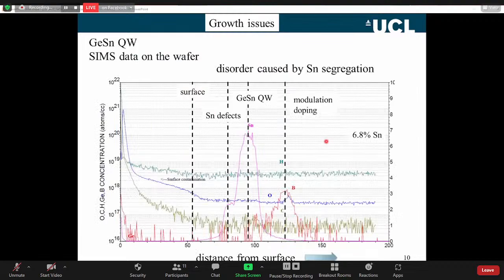When we look at what we've grown, we use a technique called SIMS. I think it's secondary ion mass spectroscopy, so it's a good way of measuring what's in your device. But there's a lot of information here. On the y-axis, I'm plotting concentration of impurity. On the x-axis, I'm plotting distance from the surface. We can chemically profile, this is a standard technique, chemically profile what we have in the system. So this is where the real surface is. This first line here, this line here is hydrogen. You can see we've got 3 times 10 to the 18 of hydrogen in the system. Hydrogen is very good at passivating impurities, so that level of hydrogen is actually quite beneficial. It passivates impurities and causes the mobility to rise.